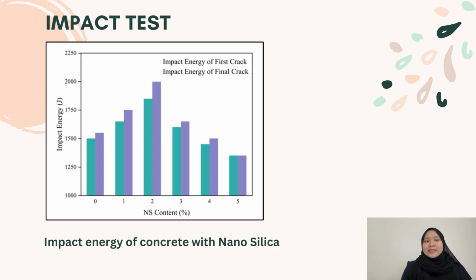The last one is for the impact test. The effect of the nanosilica content on the impact energy of the concrete is shown in the figure in the slide. It can be seen that as the content of nanosilica changes, the impact energy differs. This indicates that the nanosilica can improve the initial crack impact resistance of the concrete, but after the initial crack, the concrete continues to store energy.